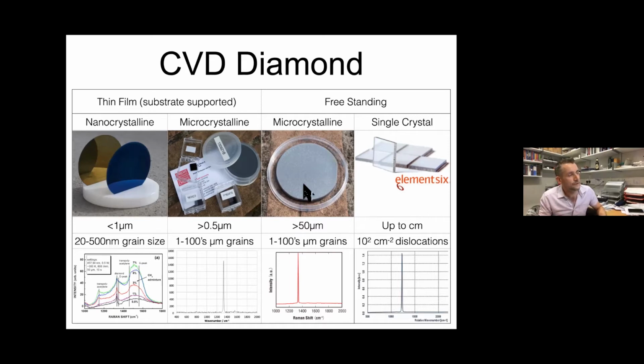We do a little bit of the window stuff for specific applications. Again, you can buy it from people like Element 6, Diamond Materials, DDK, or whatever. But what we really focus on is this side, where it's slightly thinner again. So we tend to be interested in substrate supported, because we're trying to create disruptive technologies that are a bit cheaper, and the nanodiamond stuff. The reason I put the slide in is, of course, the Raman gets worse as you go to the left. As it gets smaller, you get more and more sp2. So watch out for that.